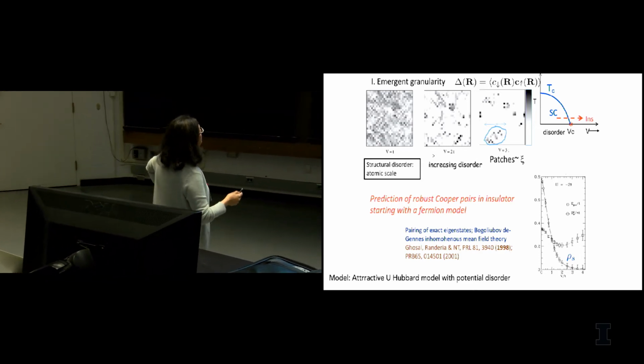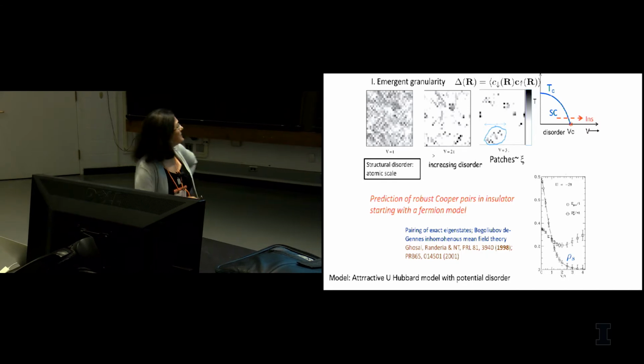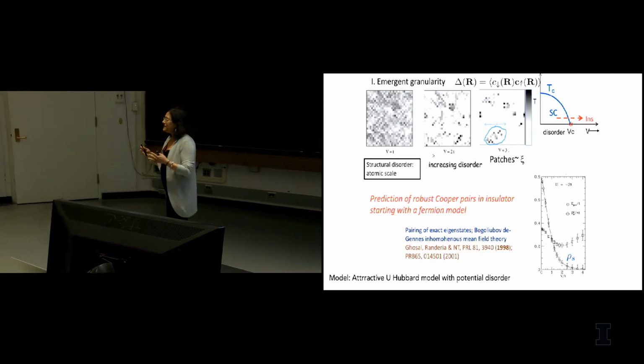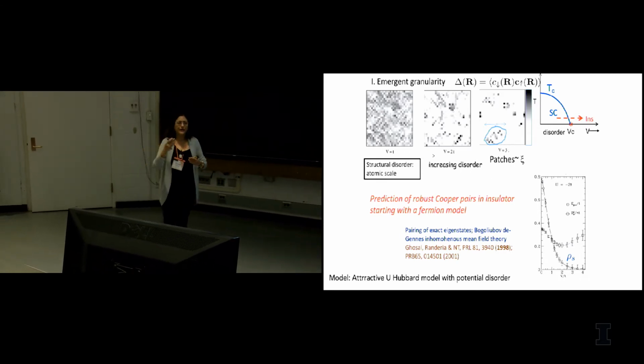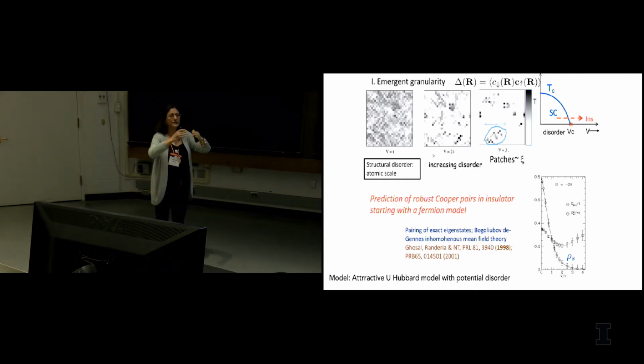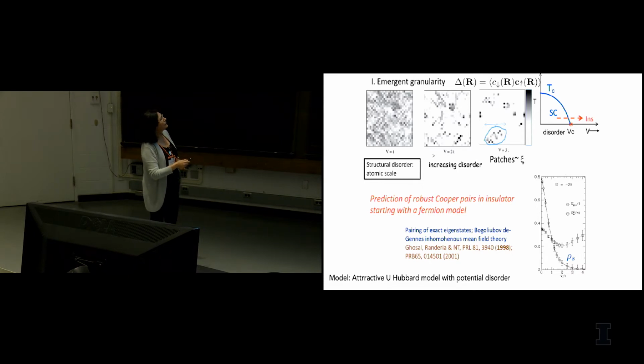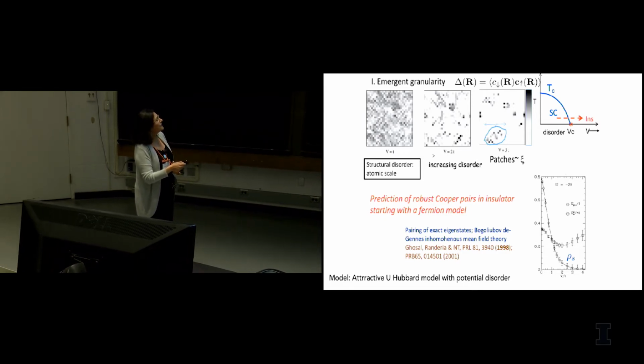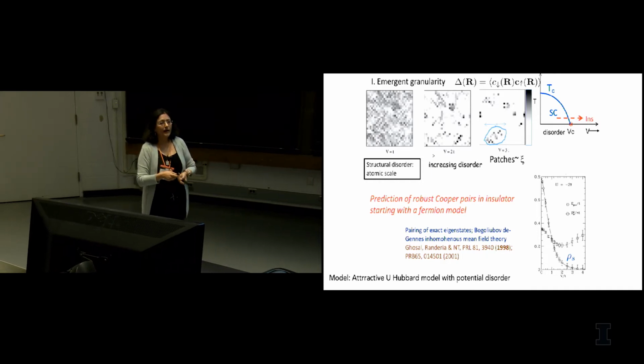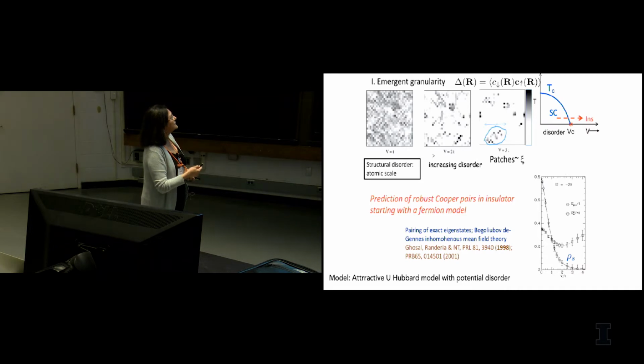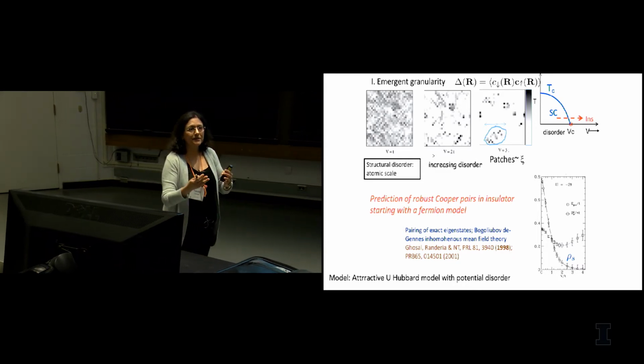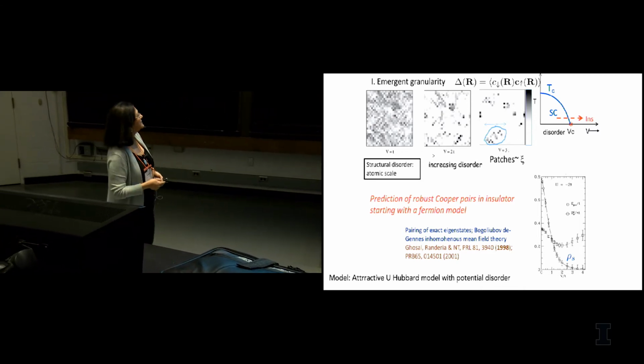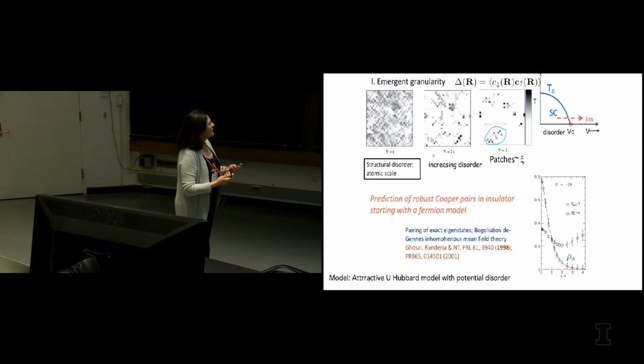So the reason behind this is that when you take disorder in a superconductor, then you get this emergent granularity. Even though the disorder is homogeneous, it creates these puddles on the scale of the coherence length, and these patches are coherent within the patch, but between patches, they may or may not be coherent. So when you have a superconducting state, the phases on the different grains are locked by the Josephson effect, by the tunneling of Cooper pairs between these grains. On the other hand, when you enter the insulating phase, in that region, due to quantum fluctuations, the phases become incoherent. Now, here we actually connected with some of Tony's work.